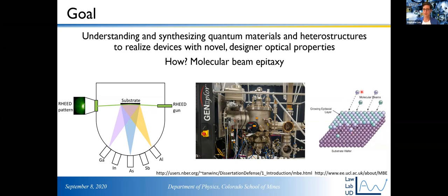And if you have, for example, gallium atoms and arsenic atoms hitting the substrate, you can grow one layer of gallium arsenide at a time. Literally a single layer of atoms, and then the next layer of atoms, and then the next layer of atoms, and so on. Epitaxy just means that the film that we are growing has a crystalline relationship with the substrate. That's what epitaxy means. And so this is the major technique that my lab uses.